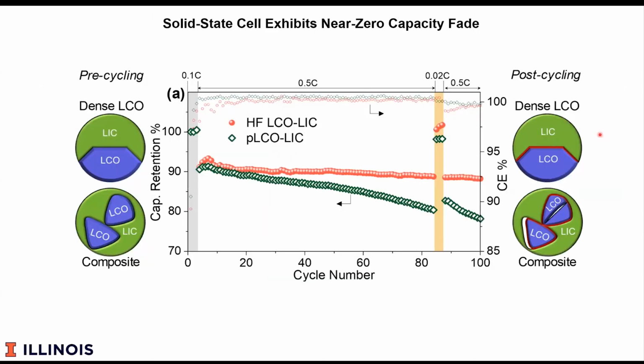One thing that, while it's only preliminary, we're quite excited about is that when we use a highly faceted system, the capacity fade is near zero. It's only a few percent over 100 cycles, where the exact same materials made up using a composite, so a powder, the capacity is fading much more dramatically. For those of you who aren't really in the battery field, just ignore the data after about 80 some cycles here. We've just varied C rates, stepped up, stepped down, and things like that. Another important parameter up here is Coulombic efficiency. You want this number to be high. It is. It's basically 100%, meaning that electrons aren't being consumed in the system.